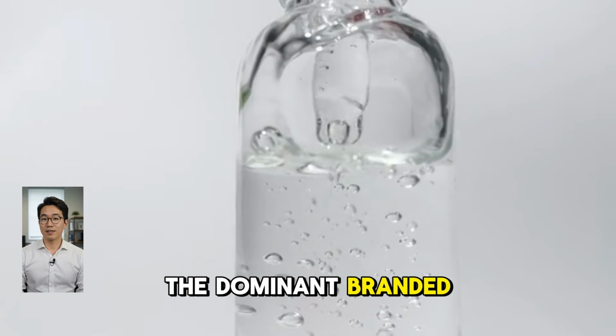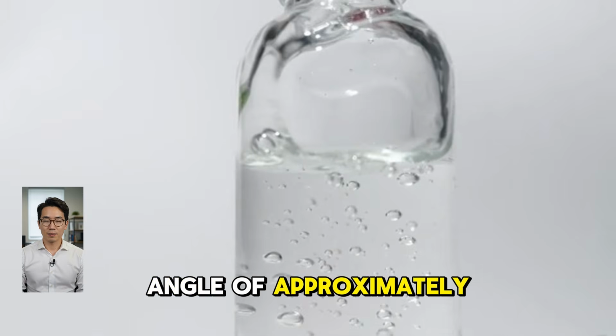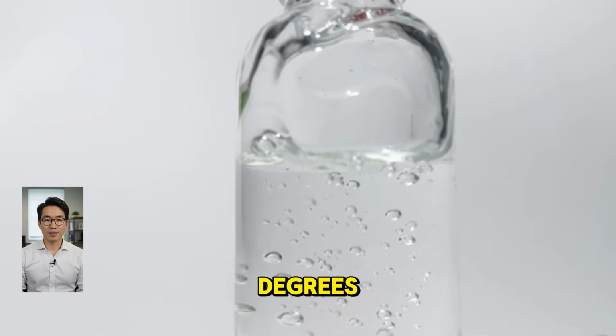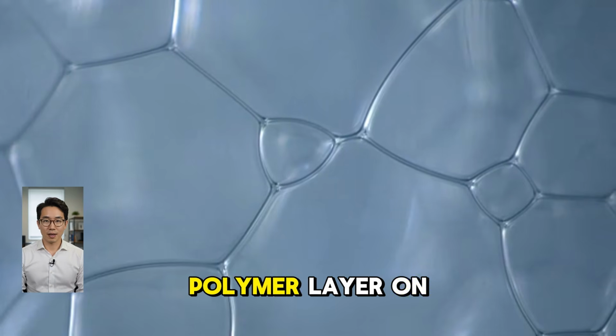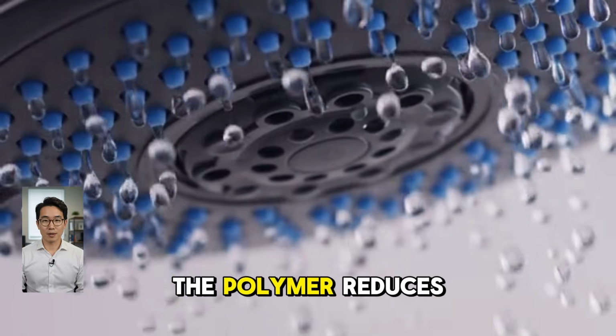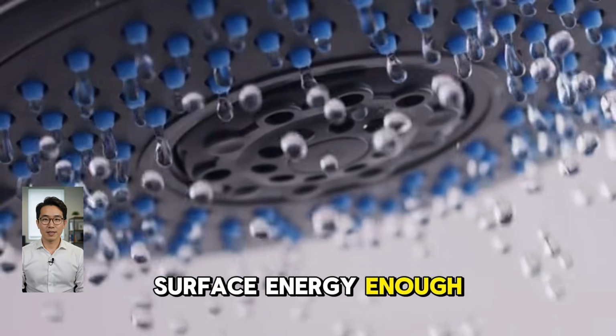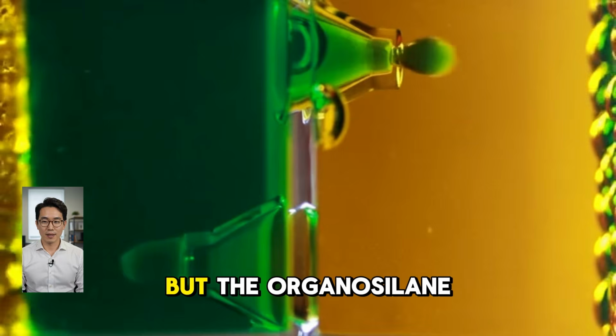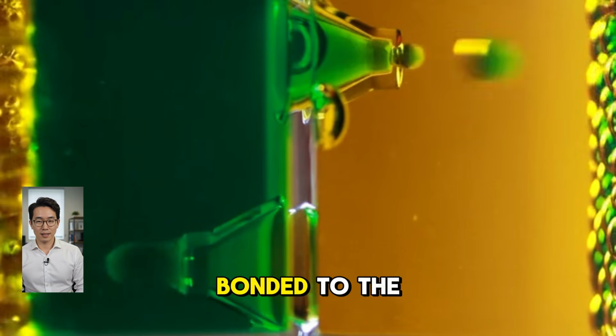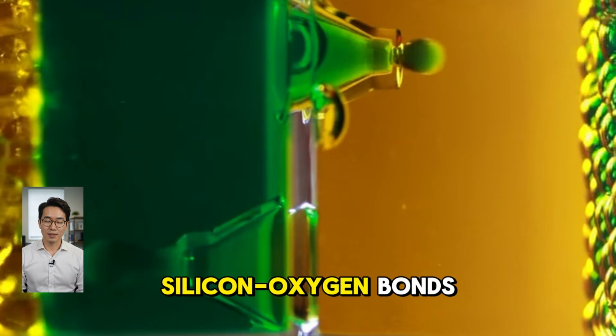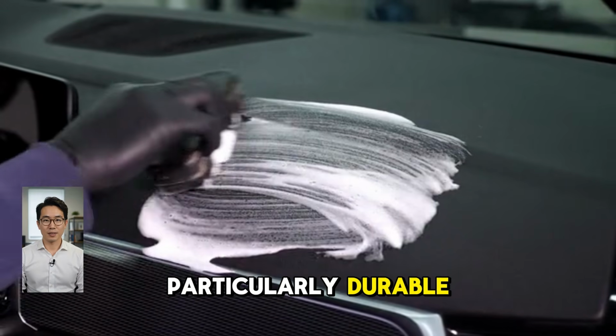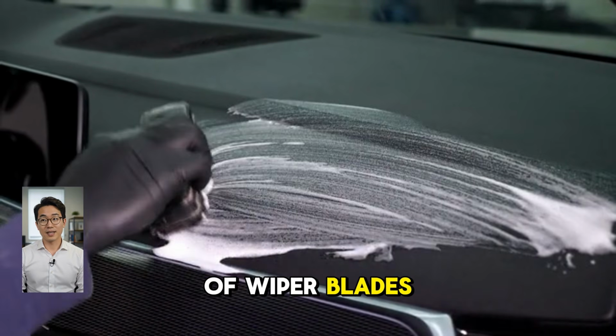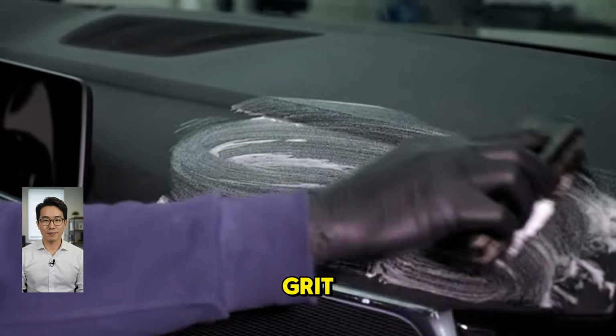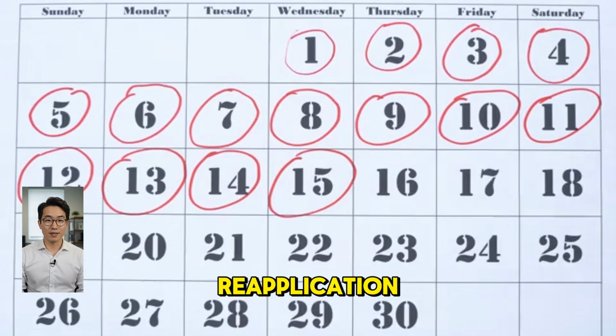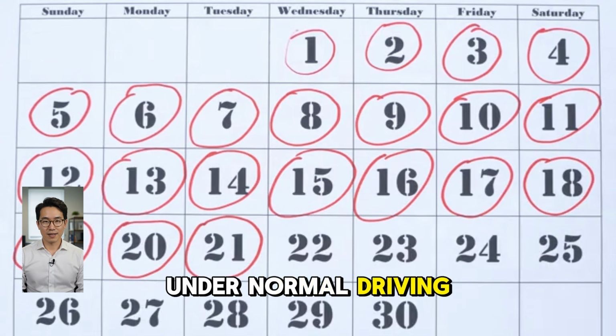Rain-X, the dominant branded glass treatment, achieves a contact angle of approximately 90 to 95 degrees by depositing an organosilane polymer layer on the glass surface. The polymer reduces the glass surface energy enough to cause water beading, but the organosilane layer is chemically bonded to the glass surface through silicon-oxygen bonds that are not particularly durable against the abrasion of wiper blades and the chemical attack of road grit. Rain-X requires reapplication every 4 to 8 weeks under normal driving conditions.